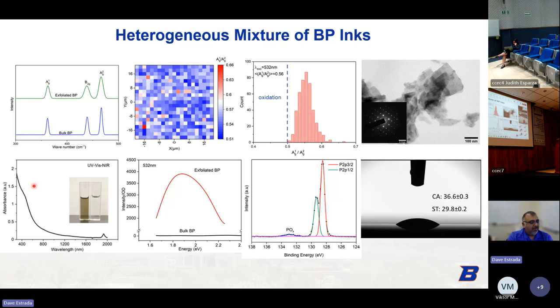And then we can look at the UV-vis and the absorption and just see that when we compare to bulk, and this is the PL, right? We have the right UV-vis spectra for this. But when we look at PL, we can look at the bulk. We have nothing in the visible. But when we exfoliate, we get to a few layers, which gives us some visible character in the PL spectra, right? And then in the XPS, we have minimal oxidation.